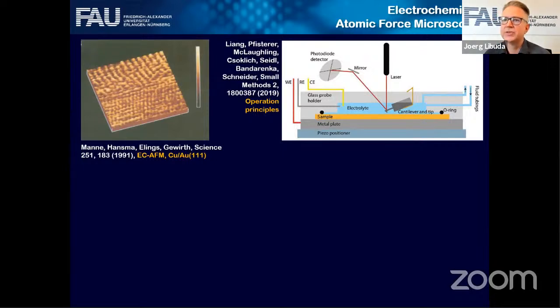Well, the alternative is to use atomic force microscopy. So what is atomic force microscopy? In atomic force microscopy, you have a tip on a cantilever, and typically in this experiment, it is vibrating. And then you detect the detuning or phase shift of this vibration optically with a laser. So that's how this experiment works. You detect this detuning when this tip comes into contact with the sample and feels the forces between the tip and the sample.